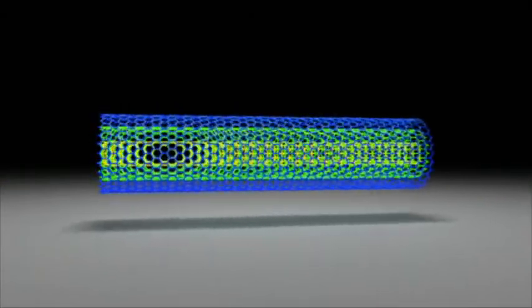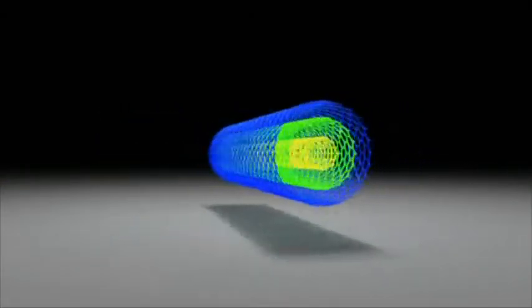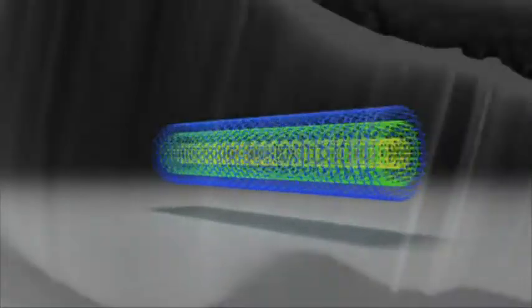The Goddard samples were grown multi-walled, so they're not just single-walled nanotubes, and they're also oriented straight up and down. The reason that the oriented samples are darker is because they're low density. Light can go in, gets rattled around in there, and it gets absorbed.